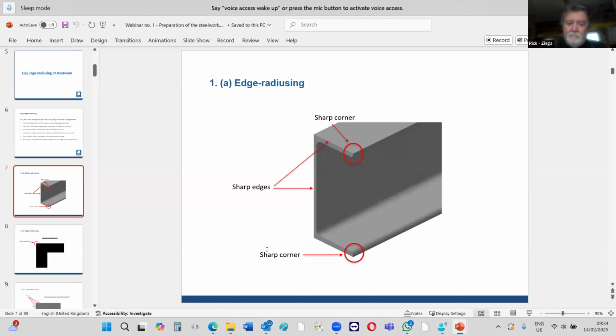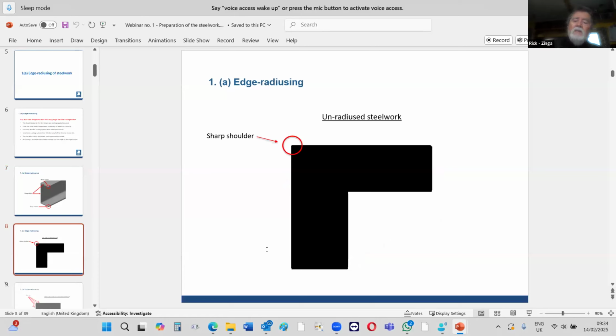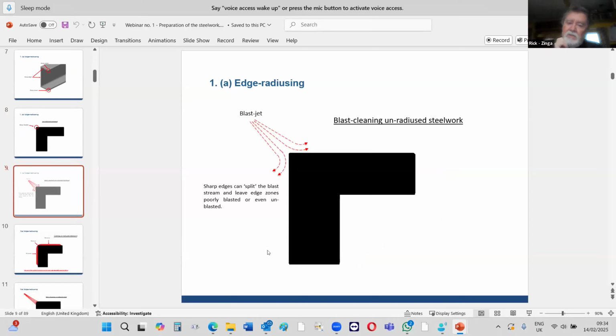So on a cut edge, you still treat that before you do any blasting or pre-cleaning. That's vital. This is just to show you, that's the sharp shoulder, and that's where the coating will pull back on either side of that sharp edge. And again, that's natural, that's the laws of physics with materials. And also when you're trying to blast it, you can split the blast.